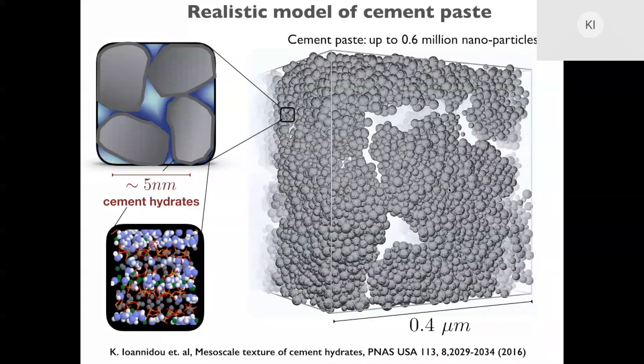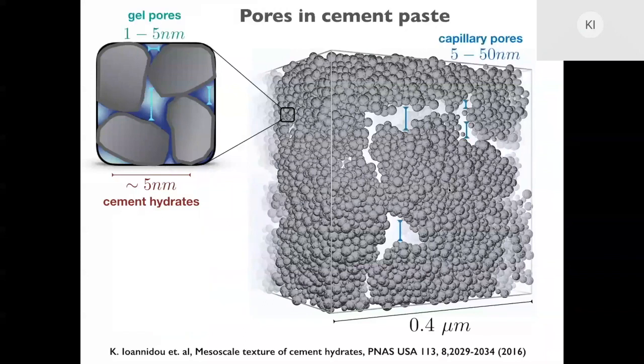And I've explained many times in the past how we've done the simulations. So what are the effective interactions arising from ion correlation forces, and then with the right simulation techniques, combining Monte Carlo and molecular dynamics simulations, we can have a structure which is very heterogeneous, and it gives a very interesting pore structure that has basically the two main features that one sees in experiments for cement.